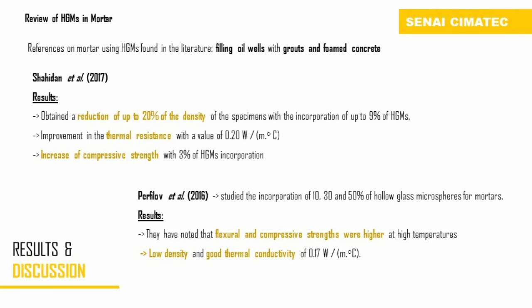Perfilov studied the incorporation of 10, 30, and 50% of hollow glass microspheres in mortars. They noted that flexural and compressive strength are higher at high temperatures, with low density and good thermal conductivity. The use of HGM in mortars provided good results in the acoustic resistance of the composites. This effect is due to the presence of empty interstitial spaces promoted by the microspheres between the minerals in the hardened state. On the other hand, these voids influenced the water absorption of the mortar.